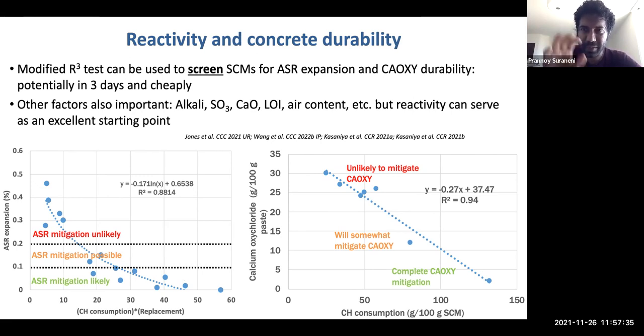So if you have materials like these, they are promising, they require further study. And these materials, which were slags, they'll probably mitigate ASR, but they may not as well. It really depends on additional factors, and long-term testing of ASR is needed. So really, this is used for screening. You can say which materials are useless, which materials are likely to be useful, and which materials are interesting but need further study.